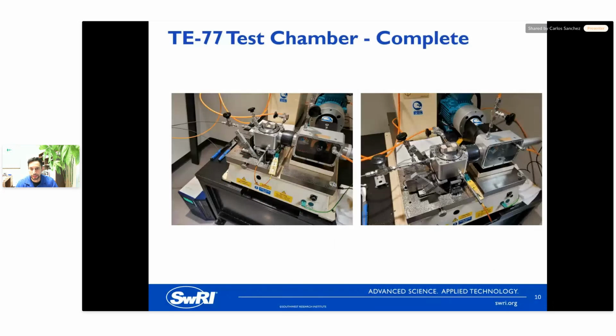Here are some more pictures of what it looks like. You can see there's all kinds of valves and ports going in and out of the system. In addition to the valves for hydrogen, there are also pressure transducers that measure the pressure while it's running. We also plumb in nitrogen gas that's used to purge the system before and after each test. We also use the nitrogen to qualify the system, running tests in nitrogen to see if there's any effect, nitrogen gas versus hydrogen gas.